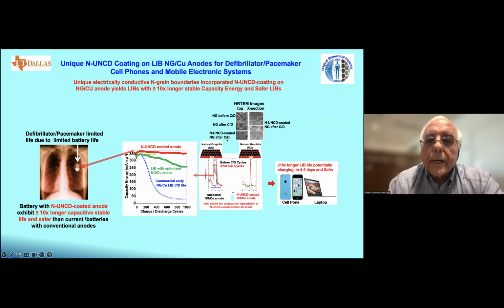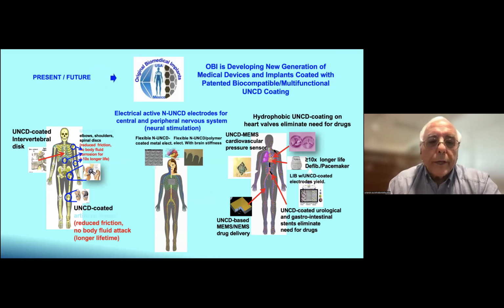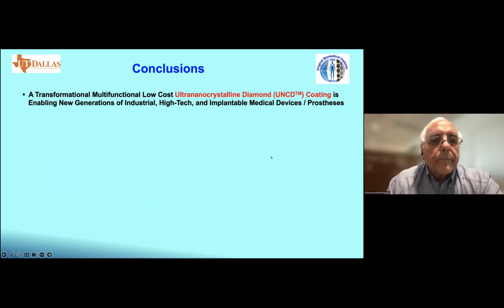And now we demonstrated that if we coat this graphite with our electrically conductive NUNCD, we can get flat capacitive energy as a function of charge-discharge, as opposed to the degradation observed in all these commercial graphite on copper anodes for lithium-ion batteries. So we think that we are going to be able to produce a new generation of implantable medical devices. Also, we are developing electrodes for neural stimulation, and a transformational, multifunctional, low-cost ultrananocrystalline diamond, enabling a new generation of industrial, high-tech, and implantable medical devices and prostheses.